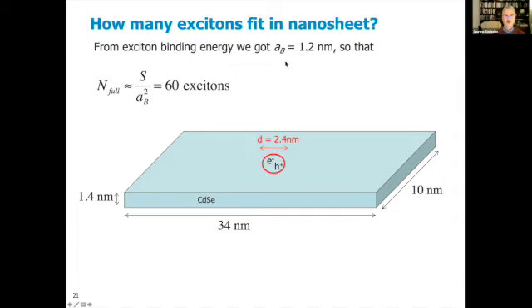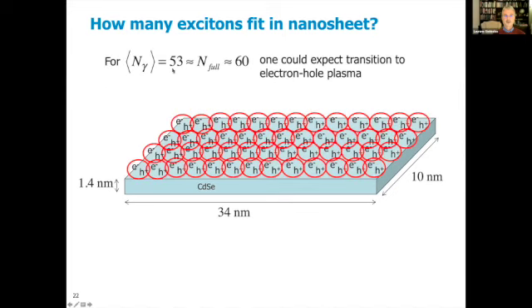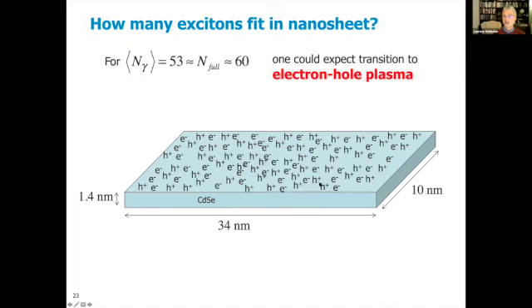But first of all, let's say from the Bohr radius, we get that the cadmium selenide nanosheet would be fully filled with excitons if we would have 60 excitons. Here there's a factor of pi missing, I see. So you would expect for 53 photons absorbed per nanosheet that you're close to a nanosheet completely filled with excitons, close to the 60 that would fit in the nanosheet. So you could expect a transition to an electron hole plasma. That's what usually happens in bulk materials. If the excitons are sitting on top of each other, they dissociate into free charges.